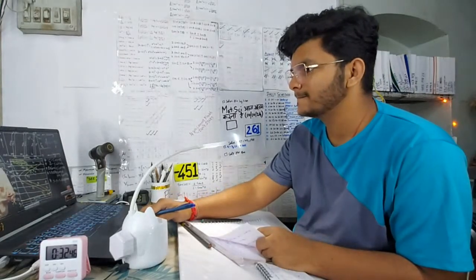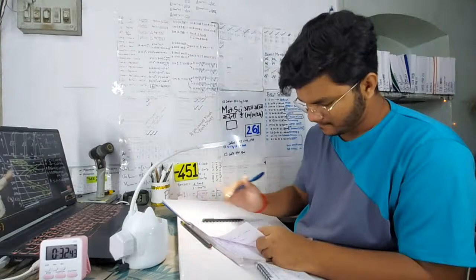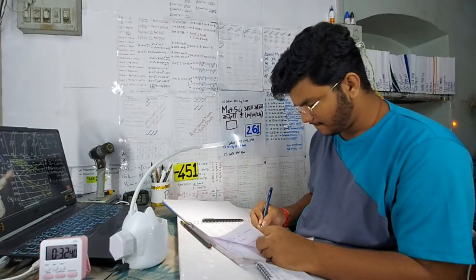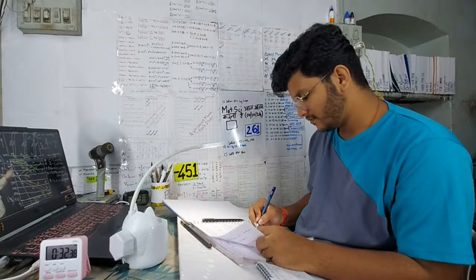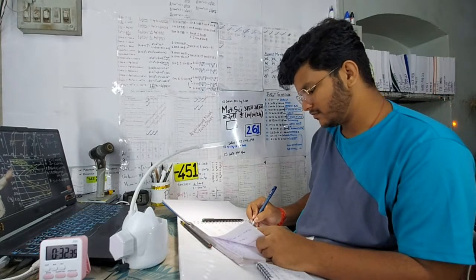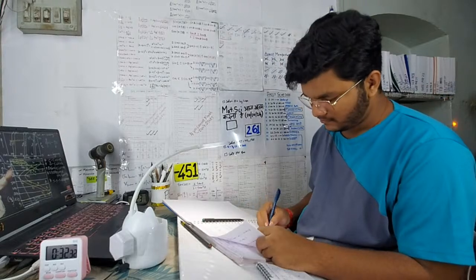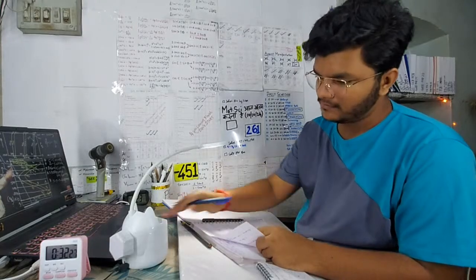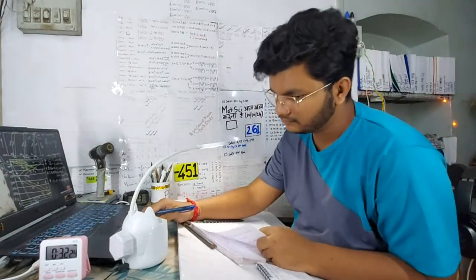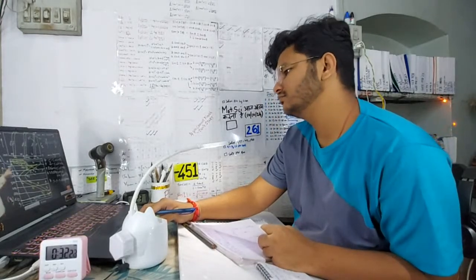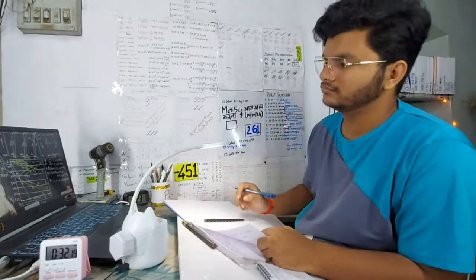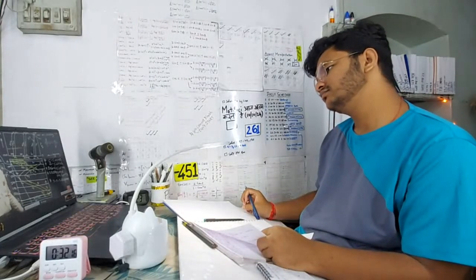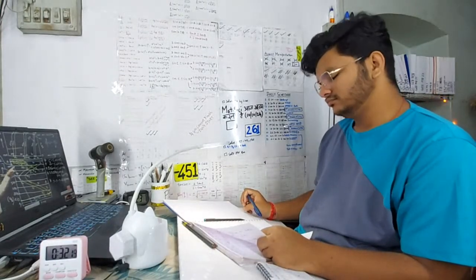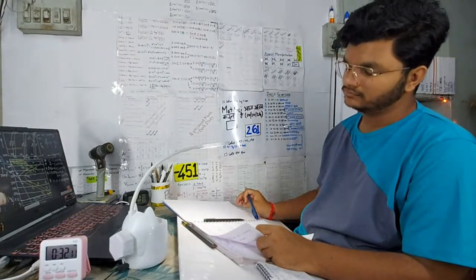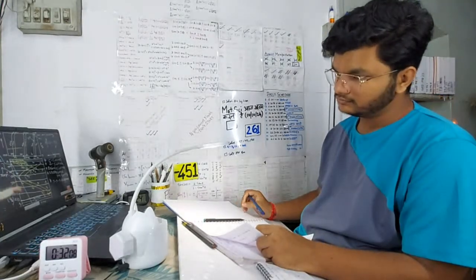Without passing through pearlite and bainite regions, is this graph. Is this cooling rate passing through pearlite and bainite? No. So without passing through pearlite and bainite regions from austenite, it is possible to obtain martensitic structure. लेकिन ऐसा by quenching the steel at critical cooling rate. Then what is critical cooling rate? Critical cooling rate is the cooling rate which touches the nose of the TTT diagram.